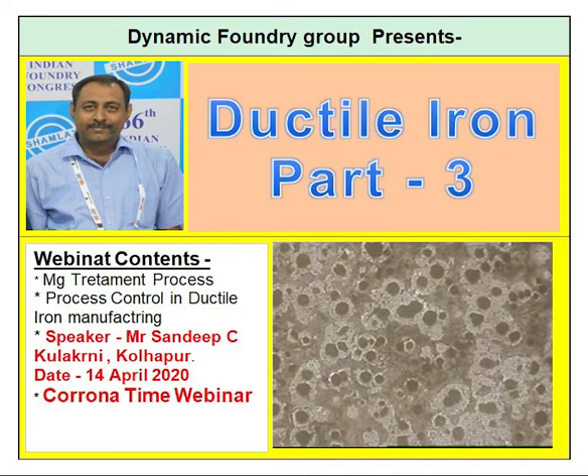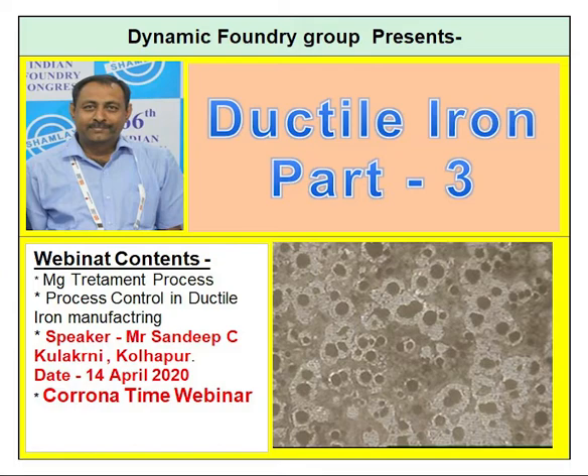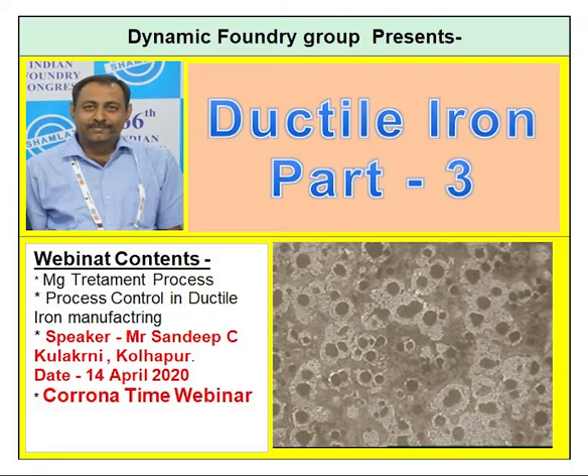Pouring with a timer is important. Deslagging is another critical factor, because without deslagging your magnesium recovery will not be adequate and you will have to add more magnesium — approximately 0.2% more. So you have to add 0.2% more magnesium if you skip the deslagging treatment. Optimization of tapping temperature is very important as it will help reduce energy cost as well as magnesium addition, reducing overall cost.